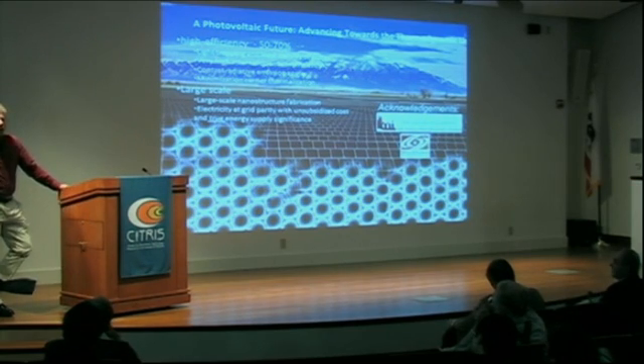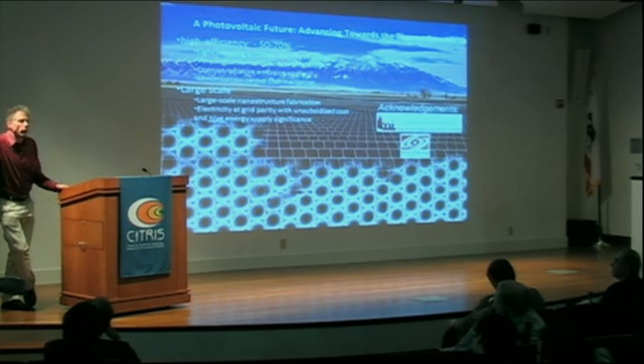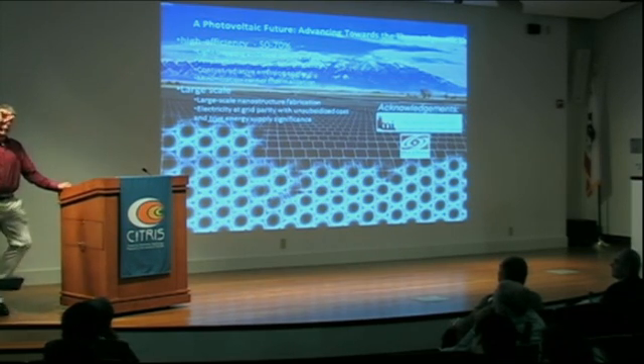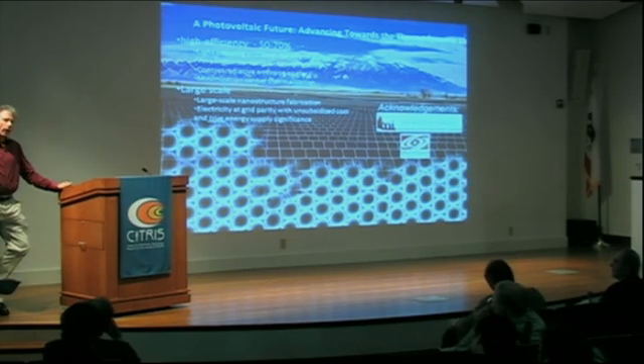Well, what's important is high QE, I would say, not high Q. Something like the metal insulator metal waveguide structure has a large local density of states that's non-resonant. So the effective Purcell factor across the whole visible and near IR is between 40 and 60. So you have to worry about the losses, but something like that. I think it's possible to build waveguide structures rather than resonator structures that don't have narrow resonances.